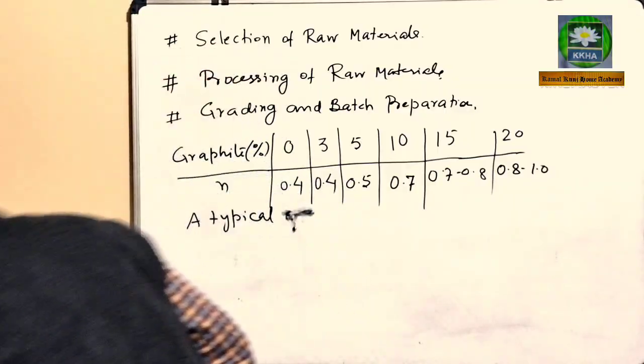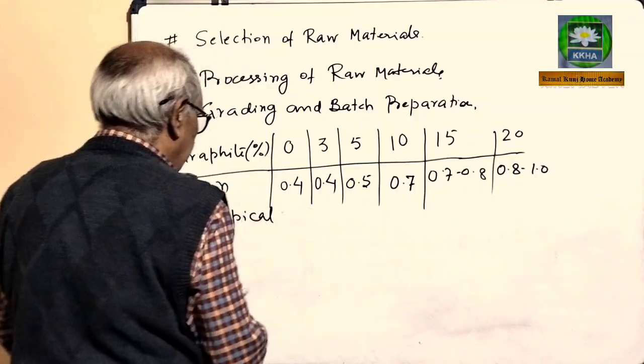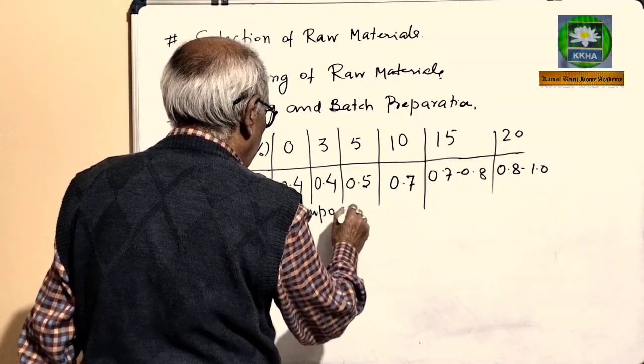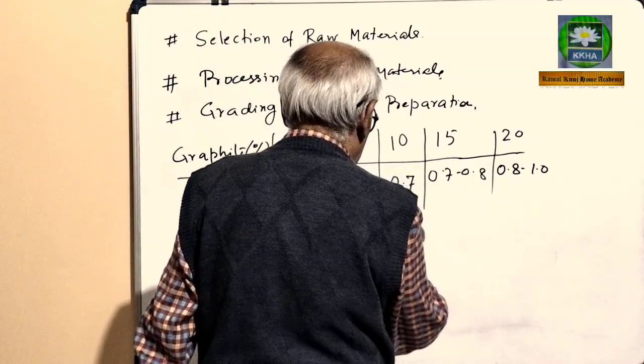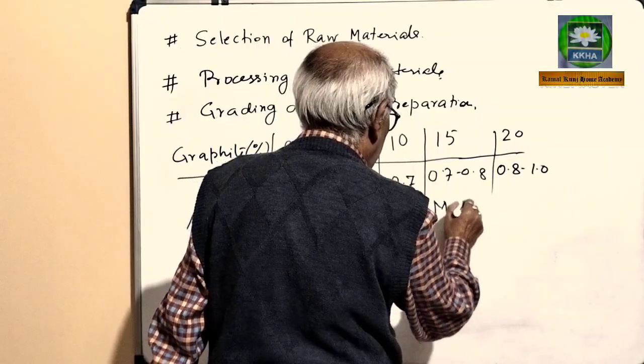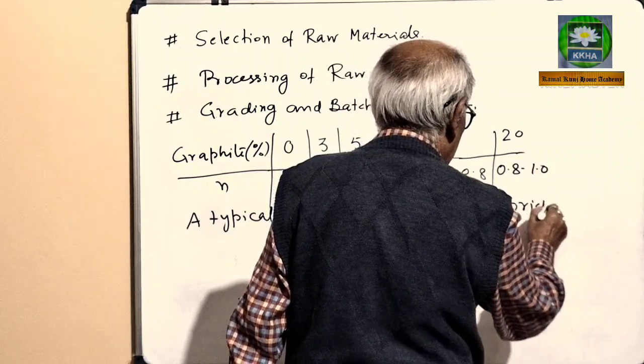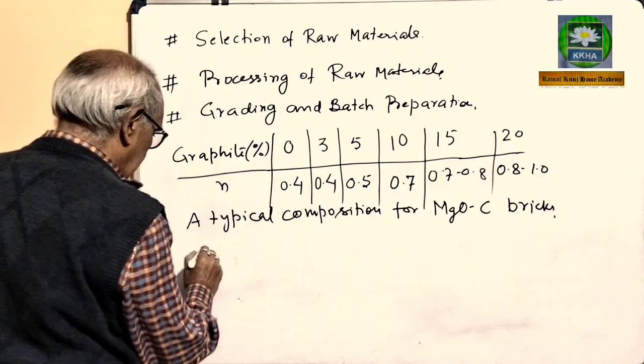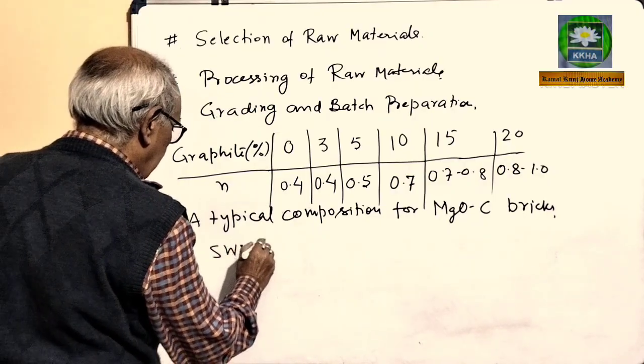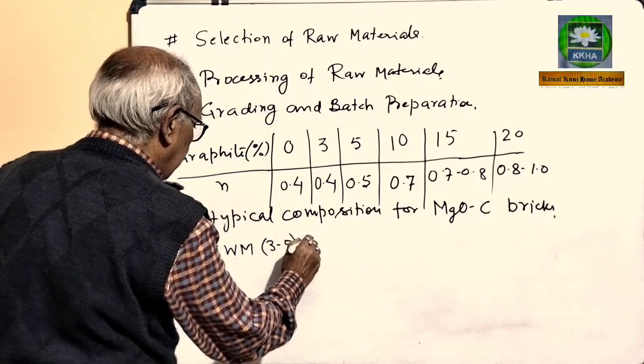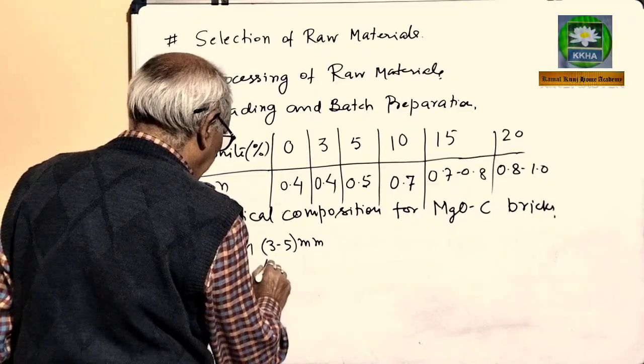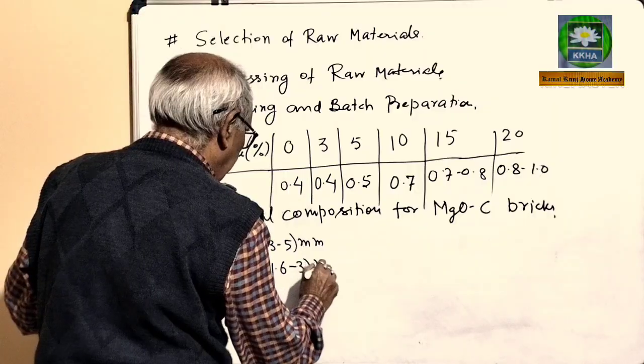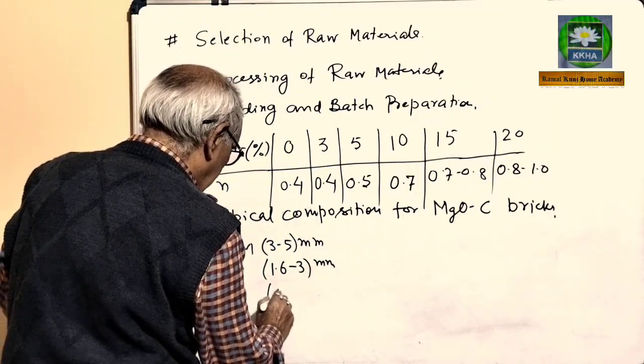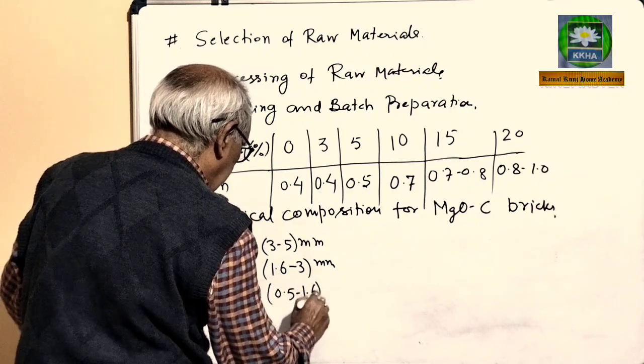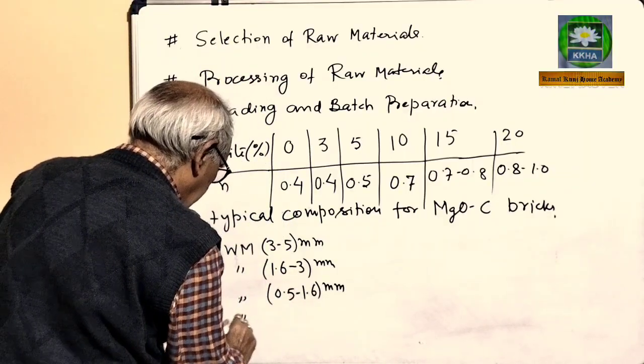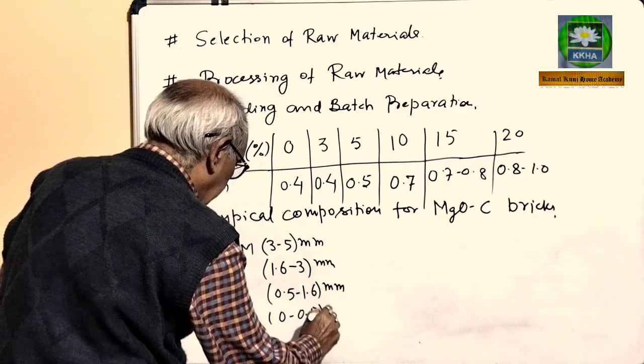Typical composition for magnesia-carbon bricks. A typical batch composition. Here, sea-water magnesia 3 to 5 mm, sea-water magnesia 1.6 to 3 mm, sea-water magnesia 0.5 to 1.6 mm, and seawater magnesia 0 to 0.5 mm,